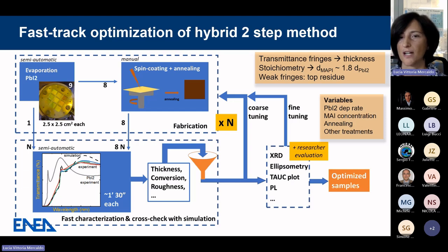In this case, we can vary all the other parameters like the concentration of the methylammonium iodide, annealing, and so on. All these films then go to the fast characterization step for the transmittance measurement. The comparison of transmittance spectra with the lead iodide alone and the full material allows us to get an idea of the stoichiometry, because we know what to expect as a ratio of the two layers, always based on densities and molar masses.